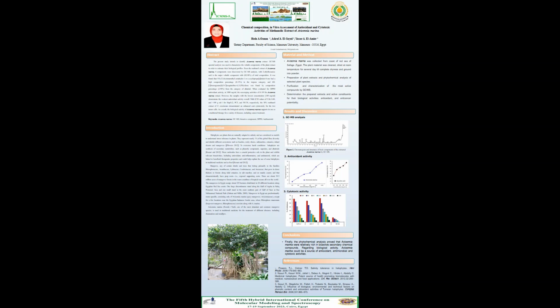Cytotoxic activity. The significant cytotoxic potential of Avicennia marina having IC50 microgram per milliliter values 61.39 for HepG2 cell lines, 76.52 for MCF7 cell lines, 60.33 for PC3 cell lines, and greater than 100 microgram per milliliter for normal cells. Conclusion. Finally, the phytochemical analysis proved that Avicennia marina was relatively rich in bioactive secondary chemical compounds. Regarding biological activity, Avicennia marina could be a source of antioxidant, antimicrobial, and cytotoxic activities.